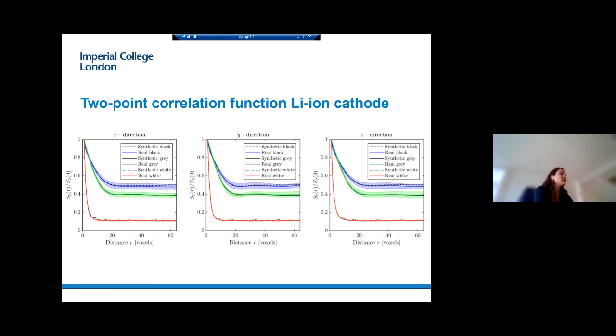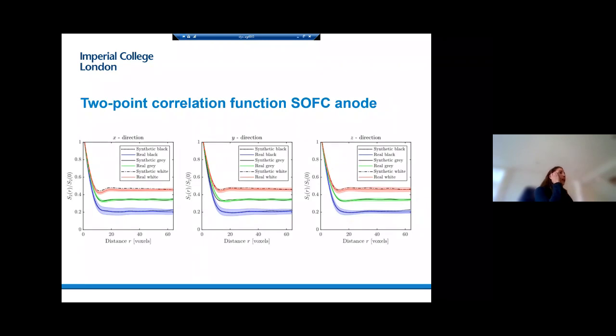So by calculating this, we can see that the synthetic images generated fall within basically the envelope of the real microstructures in terms of all the phases and along all directions. And if we see the same for the SOFC anode, we can see that not only does it fall within the means, but it also represents the same exponential type of decay. So we basically can see that now we have generated 3-dimensional realizations of the image that pretty much, based on all of these calculated tests or properties, represent the real microstructure.